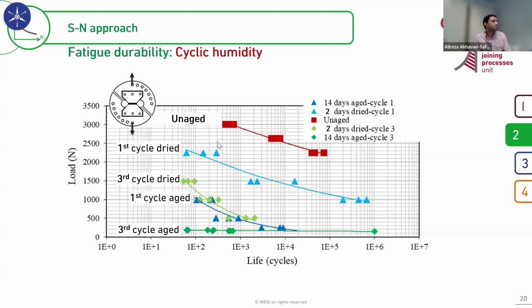Actually, the second part was not very clear to me, but maybe I can explain a bit more. Here, you see my screen, right? Yeah. Okay. So, for example, here we are talking about cyclic aging plus cyclic loading. It means that we perform cyclic aging first, and then we tested them under cyclic loading. Under cyclic aging, we have a degradation in properties. We have also static results. We have published this data in a paper, and we see a degradation in properties. This degradation in properties is a function of aging cycle, of course. But after that, we perform cyclic loading, and we know that the properties degrade cycle by cycle until the joint fails, right?